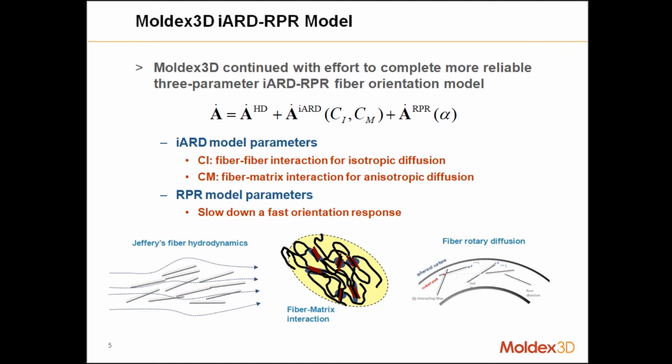First is the Jeffery hydrodynamics, as you can see in the bottom picture, and also the rotary diffusion and the fiber-matrix interaction. Including these three phenomena is very suitable for predicting the skin-shell-core orientation structure inside the simulation.